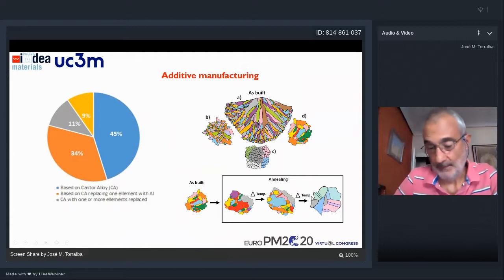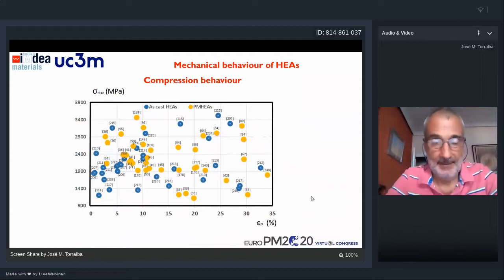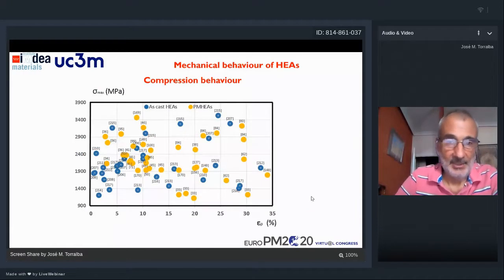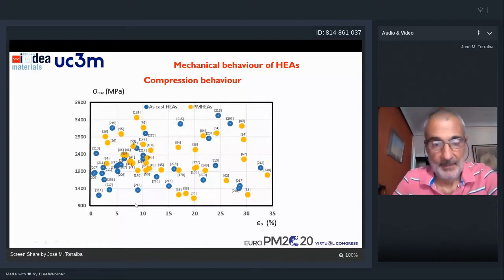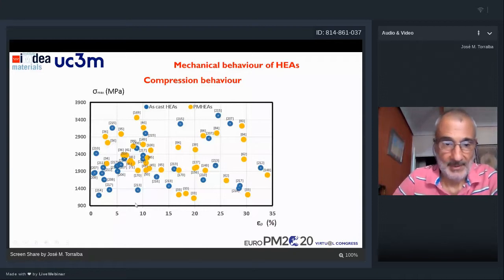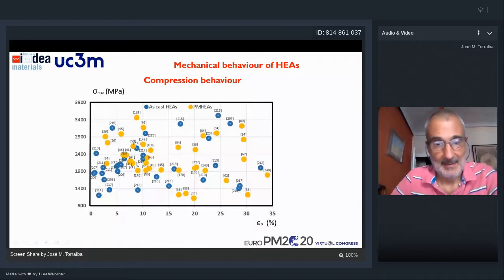in the microstructure. So let's analyze a little bit the mechanical behavior of the high entropy alloys. In this graph, we have plotted the compression strength against the deformation in percentage. So if you see the dot points, the blue points are the as-cast high entropy alloys, the ingot metallurgy ones, and the yellow ones are the powder metallurgy high entropy alloys.